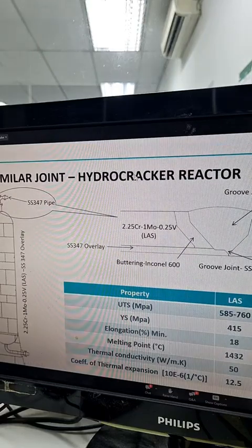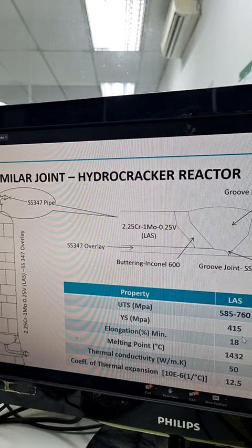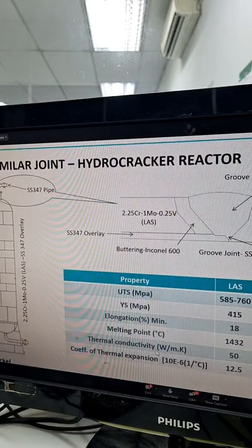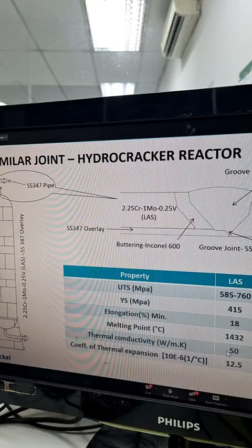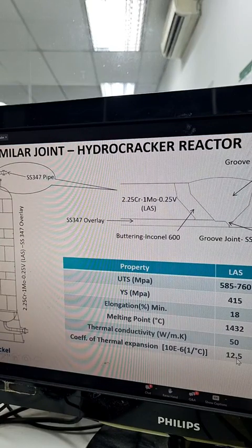A few more examples: a hydrocracker reactor, where you have 2 1/4 chrome 1 moly 1/4 vanadium which you need to join to a stainless steel 347. If you see the difference in the yield strength of these two materials, and elongation, they are vastly different, and the thermal conductivity, you can see how they differ, and even the thermal expansion coefficient. For alloy steel it is 12.5, and for stainless steel it is around 16.5, a huge difference. So the weld procedure which you develop has to be thoroughly studied and verified before such things are put in application.